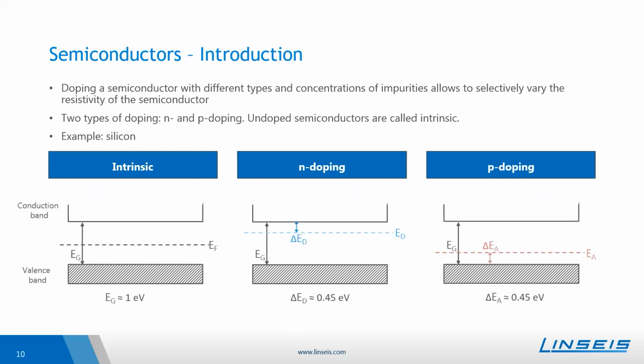So this doping also affects the schematic of these energy levels. In the case of the N-doping, the additional electrons in the conduction band lead to the creation of a new energy level. This is called the donator level, ED. This energy level is located right below the conduction band, and the ionization energy to lift an electron from the donator level to the conduction band is much smaller than the gap. As an example for silicon, this distance is in the order of 0.5 electron volts. Just as a reminder, the band gap in the intrinsic case is about 1.2 electron volts.